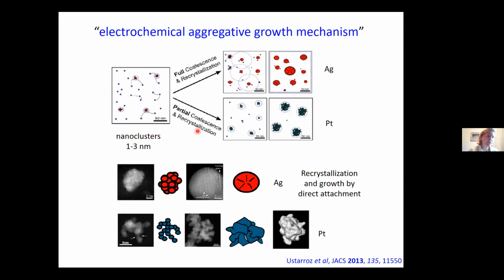And what he did is he started to really use TEM, very high resolution TEM, 3D tomography TEM, to study the structures of the particles that were being formed on the surface. And what John was postulating is that in more traditional theories, you might say that once you've got a stable nuclei, you just start to grow on top of that nucleus and you get this crystallization. John was saying that these nuclei actually will move around and they'll form aggregates. So you can see here, and these aggregates with time may end up coalescing into a crystallized particle or, depending on the timescale, just stay in this aggregate form. And so this electrochemical aggregative growth mechanism hadn't been really postulated before, but you're seeing this prominence of it now being described in the literature.